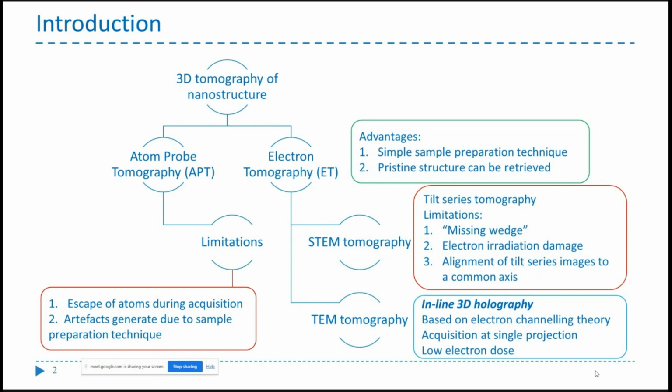Okay, and STEM means high electron dose rate, and high electron dose rate per pixel. So for electron beam sensitive samples, it is dangerous, it is detrimental. And another thing is the alignment of tilt series images in a common axis. So these are the limitations of STEM tomography. So we were interested in TEM tomography.